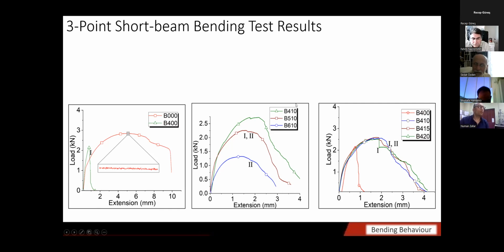You mean between the core and the sheath? I mean the wire core diameters of the wires which have constituted the wire reinforced components substantially influence the bending behavior. Here is another example. Increasing the core diameter reduces the load at failure and also the extension. And here I have compared, if you don't see this, this one, 410, 415, and 420, they have all in situ boroided phases. Their bending behavior appears to be similar. And the 400 does not have any boroided cores, so it has a lower load and a lower extension.